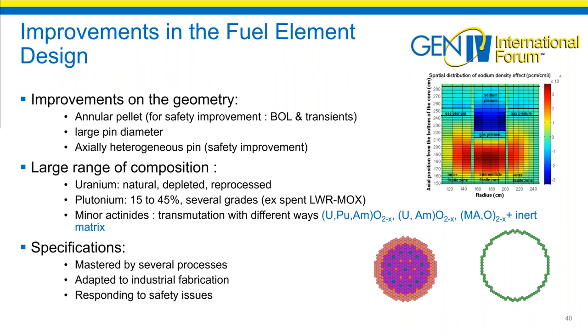We have a large range of composition, not only with the uranium, but also for the plutonium. We can take into account in a fast reactor from 15 to 45% of plutonium with several grades. And we have demonstrated that the minor actinide transmutation is possible under different ways, diluted in the driver fuel or in dedicated fuels like targets or blankets.